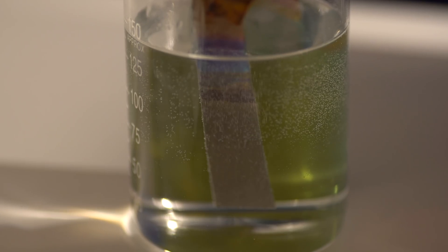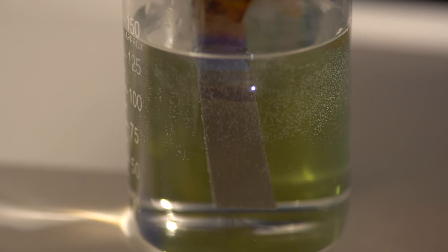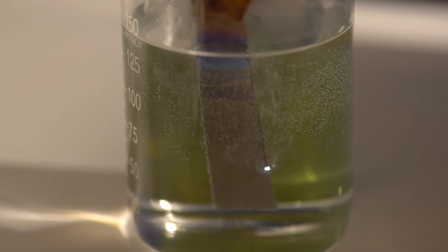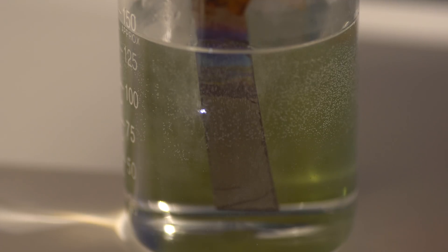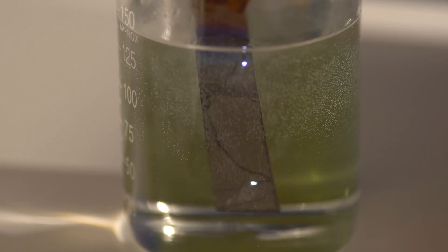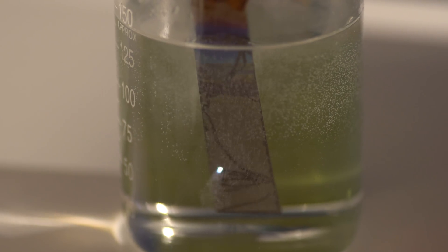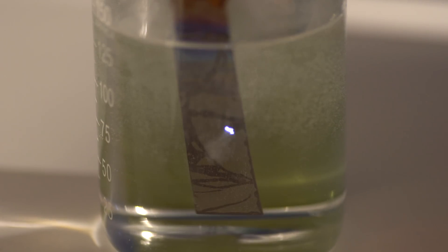By the way, while I was experimenting with different electrolytes, I found one interesting effect. In the solution of sodium phosphate, at voltage of 110 volts, the niobium plate began to be widely plasma-anodized, with spark discharge. Sparks run on the surface of the metal, leaving behind a trace of oxidized metal. It looks very fascinating.